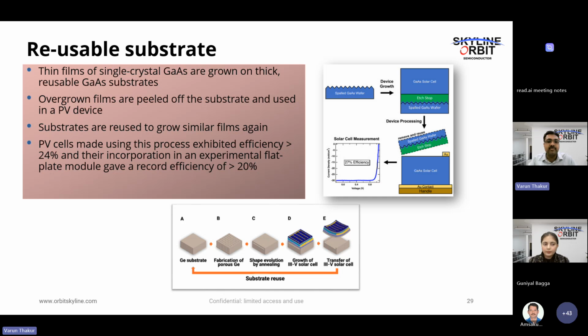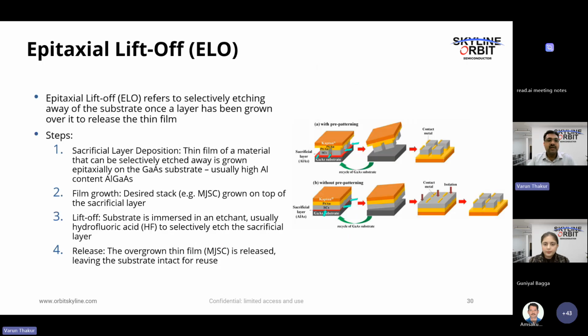The problem here is that sometimes these free floating films will crack or get destroyed. So this is not without its own set of issues, but they have been proven to give an efficiency of more than 20 or 25%. So epitaxial liftoff is the process through which we can achieve this. So what I was telling, I can explain it much better here. As you can see in this schematic, we deposit a sacrificial layer, a thin film of a material which can be selectively etched away.